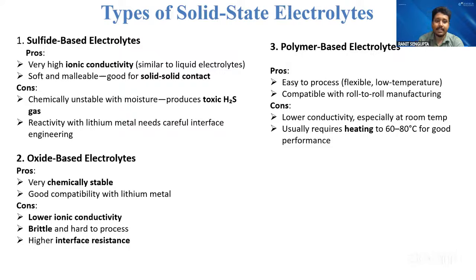If we use the sulfide based electrolyte, we can charge our battery pack up to 3C, 5C rating. That means your battery pack takes roughly 10 minutes to fully charge, and you are not damaging your cells. This type of cell has high ionic conductivity, meaning lithium ions can move very fast. That means higher charging current and higher discharging current, so we can get better life as well as fast charging and fast discharging, but it is chemically unstable with moisture.